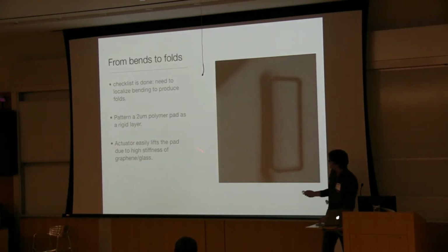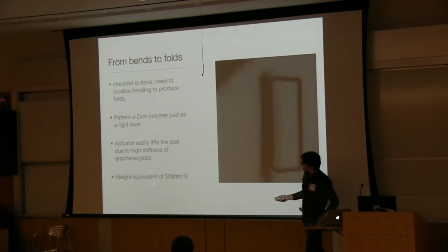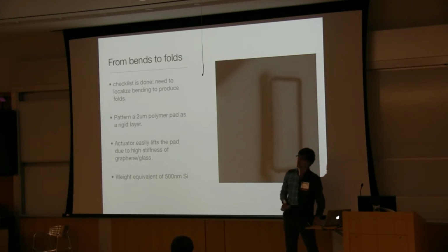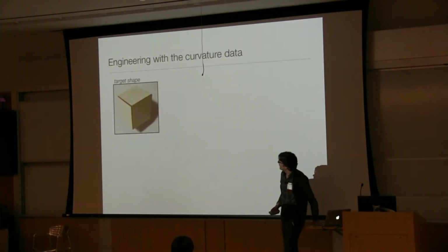Now what's cool is that this pad is quite heavy. It's much, much thicker than the bimorph, but the bimorph is able to easily lift this object. And in fact, if you work it out, this is the weight equivalent of roughly 500 nanometers of silicon. So the force output here is actually large enough that you could seriously think about a wide range of very serious functional payloads. But let's say that you don't just want to bend them, you actually want to build complex stuff. How do you go and do that?